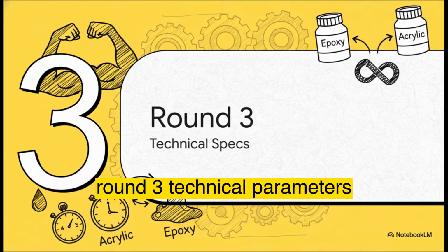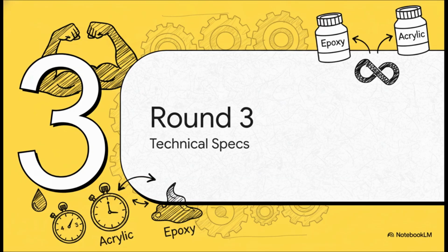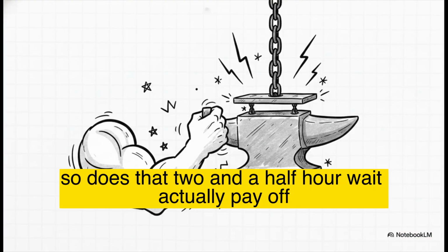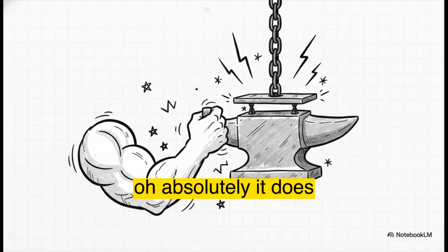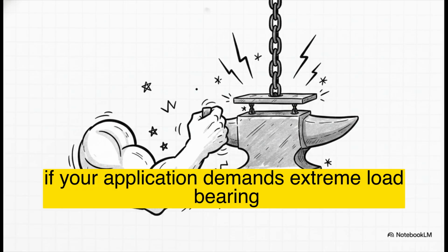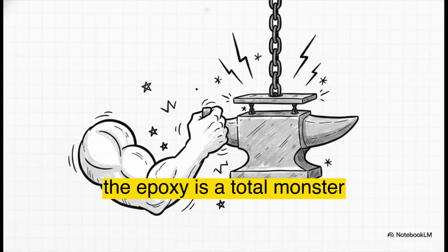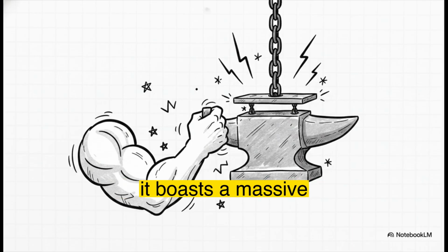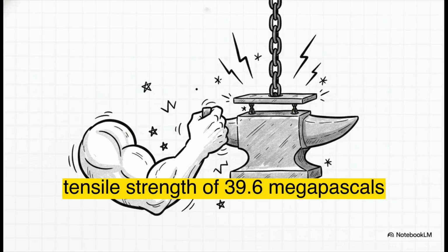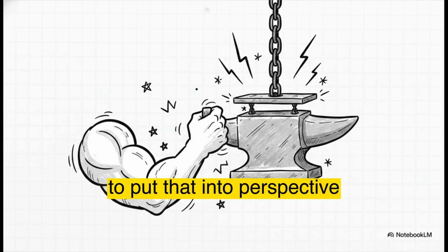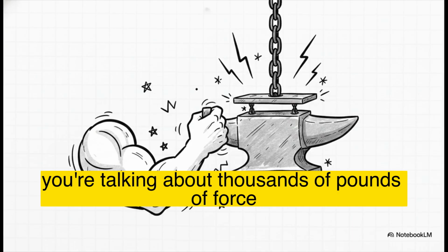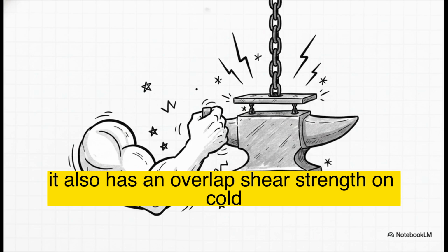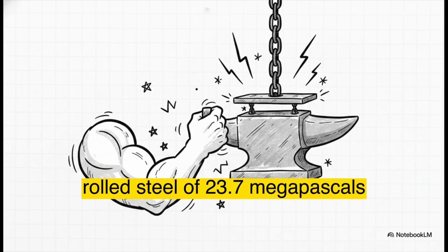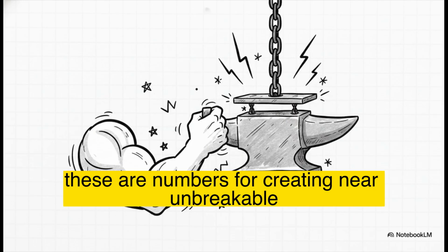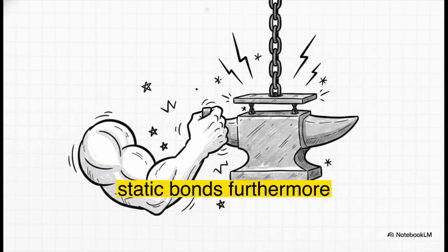Round 3. Technical parameters. So does that 2.5-hour wait actually pay off? Oh, absolutely it does. If your application demands extreme load-bearing, the epoxy is a total monster. It boasts a massive tensile strength of 39.6 megapascals. To put that into perspective, you're talking about thousands of pounds of force per square inch. It also has an overlap shear strength on cold-rolled steel of 23.7 megapascals. These are numbers for creating near unbreakable static bonds.